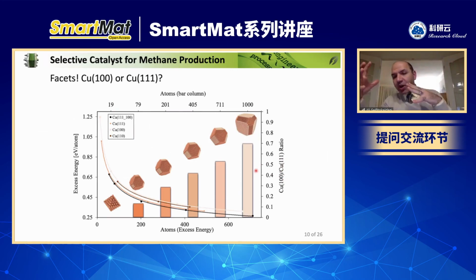So an enlarged particle size that we obtain through sputtering, let's say if you sputter 100 nanometer particle size, then you have multicrystalline or polycrystalline copper. So you have those 100 facets. And in different works, people showed that when you have 100 facets, then CC coupling is easier. So this can be one reason.